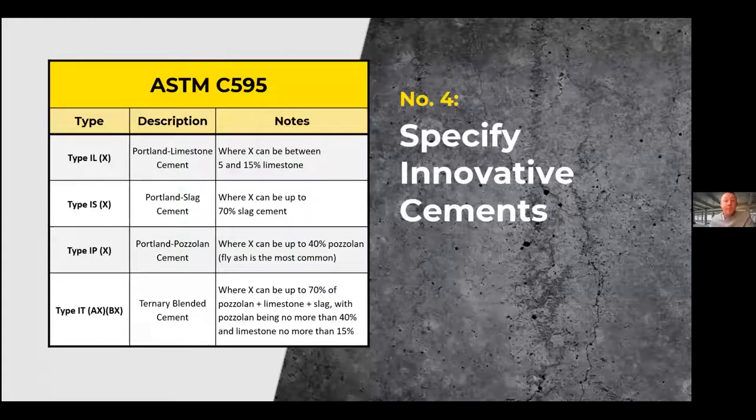Without going into too much detail, during cement manufacturing, limestone is fired in a kiln at high temperatures, and the fuel burned during this process is a contributor to global emissions, while the chemical breakdown of limestone also releases CO2. So with blended cements, we're able to reduce the amount of material that is fired in the kiln, and thus directly and simply reduce the carbon emissions.